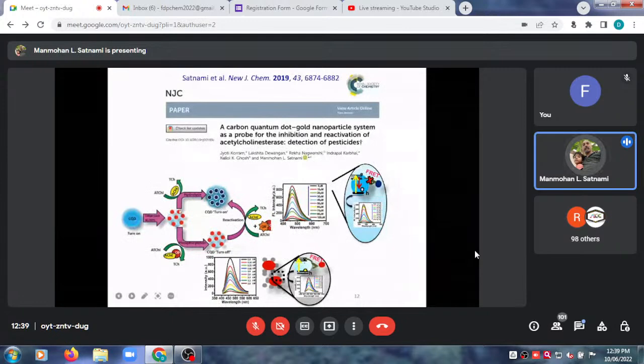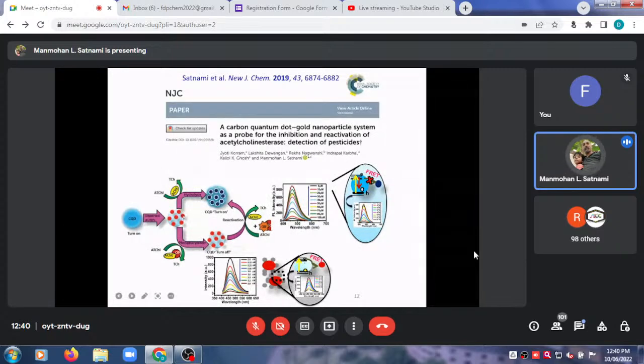Then after adding gold nanoparticle, we added acetylcholinesterase enzyme and acetylthiocholine. So this acetylcholinesterase enzyme catalyzes the hydrolysis of acetylthiocholine, and thiocholine is produced, which is a sulfur containing compound. Then as this thiol containing compound is released, it will interact with this gold nanoparticle. The gold nanoparticle will start aggregation, and its size will increase, and it will release from the surface of the carbon quantum dot, and therefore the fluorescence intensity of this carbon quantum dot will recover. So this is called fluorescence recovery. The process is called turn on. The fluorescence turn on. So you can see this is now looking fluorescent.